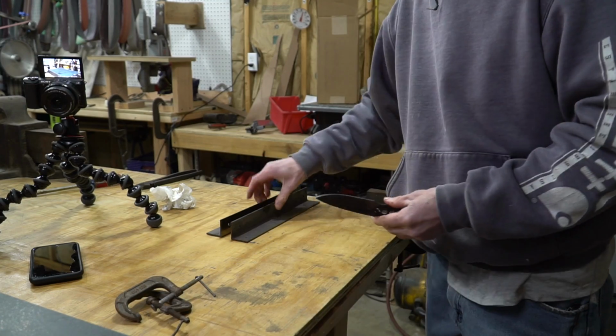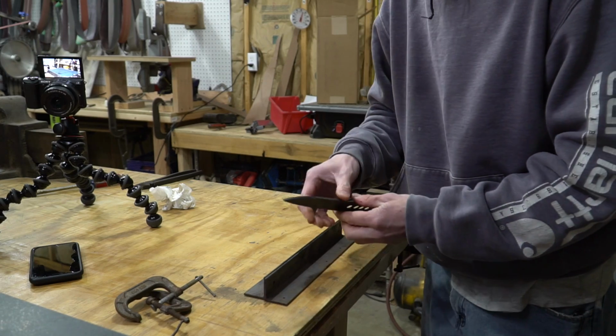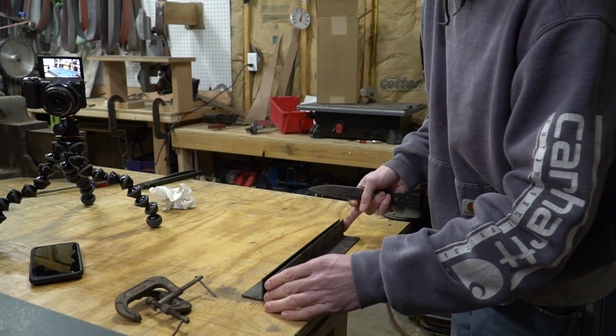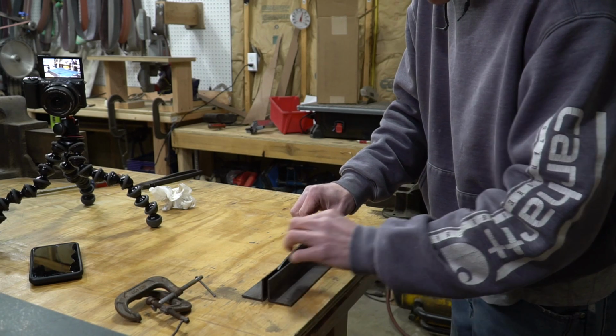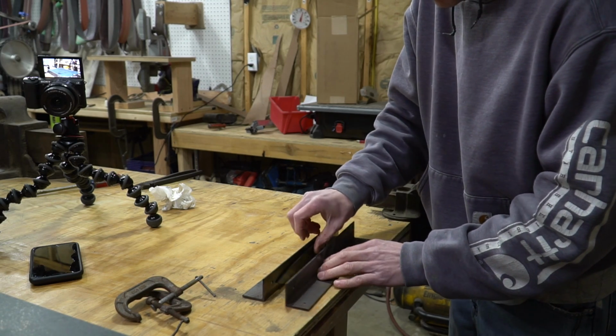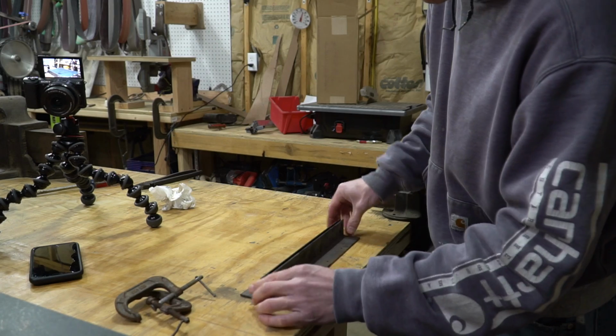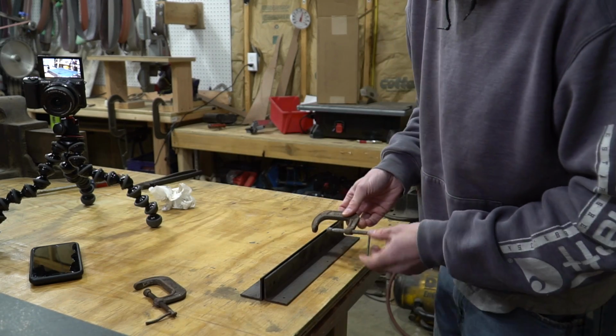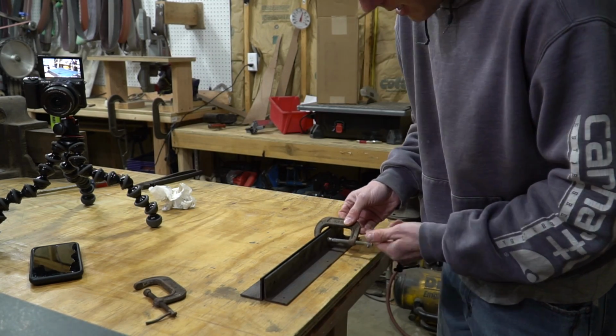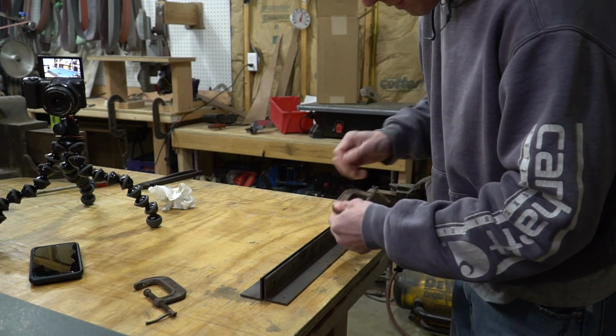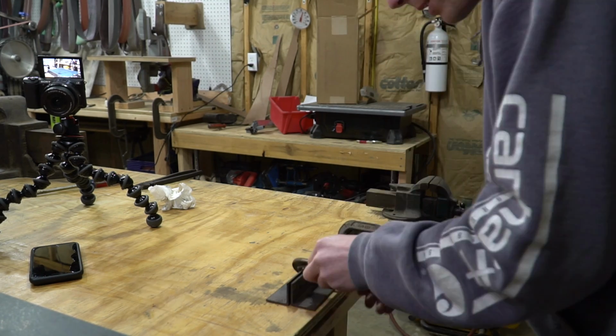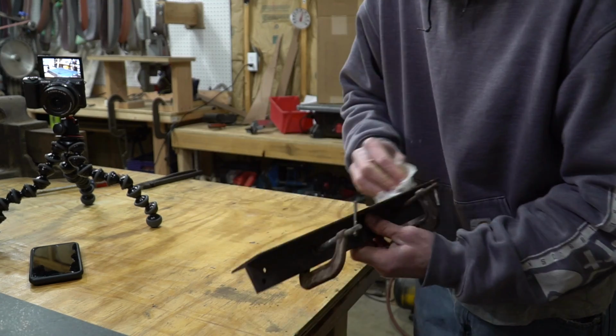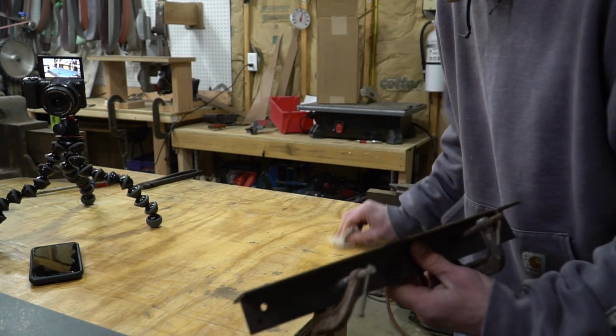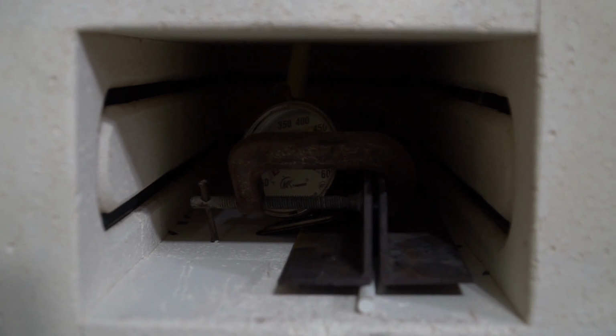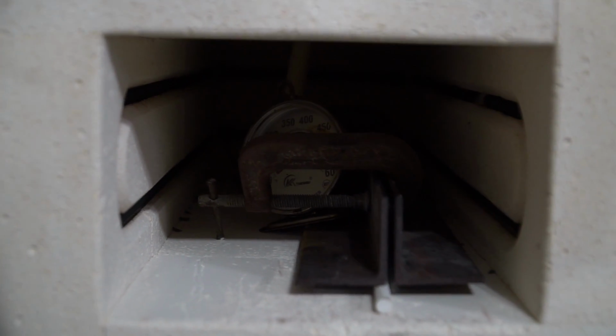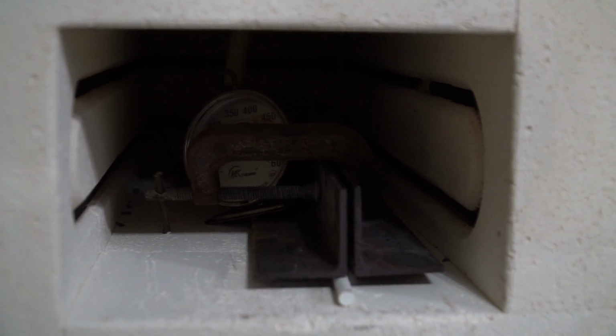Now what I'm going to do is take our same pieces of angle iron, and we're going to put the blade between them like this, and we're going to do a clamped temper. That way we remain straight during our tempering process. Our clamp temper just involves taking a couple of clamps, clamping this thing straight. Wipe the oil off of here. Oil gets everywhere. A tight squeeze getting everything in here, but we've got our oven thermometer in there so we can closely monitor the temperature.